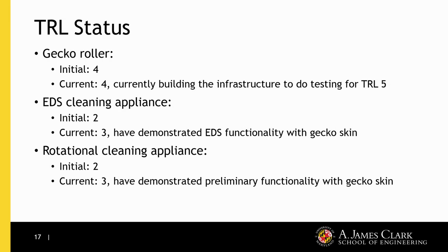So in terms of TRL status, the initial was initially when we wrote the proposal. Current is our current state now. So we have shown that the gecko roller is quite effective at picking up dust off of hard surfaces. We did some initial work looking at ortho swatches, but we haven't repeated that using simulant yet. The EDS cleaning appliance is also quite effective at removing dust from the gecko skin. The rotational cleaning appliance, we're still building up that test stand, but we have demonstrated it at a lower fidelity and also seems to be quite effective at removing dust from a surface.